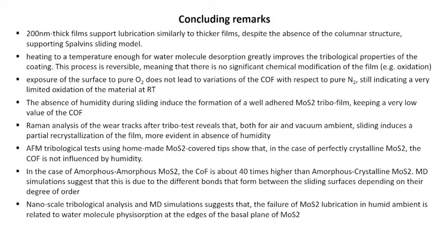And we also found that in absence of humidity, we have the generation of a tribofilm, which is very strongly adhered to the surface. And this is probably the reason why, in absence of humidity, we have this very good tribological performance of MoS2. We also found by means of Raman analysis that, in both conditions, in presence or in absence of humidity, the sliding induces the recrystallization of the film that probably contributes to the good tribological properties of this system.